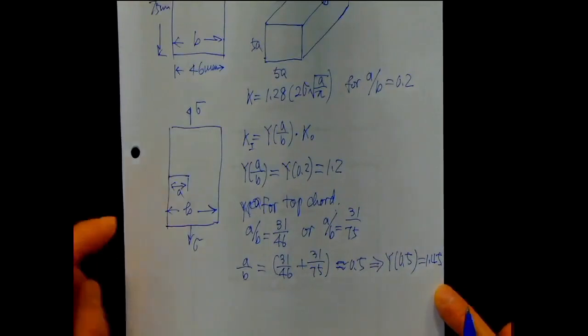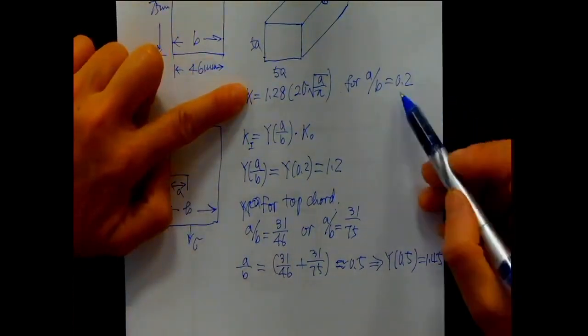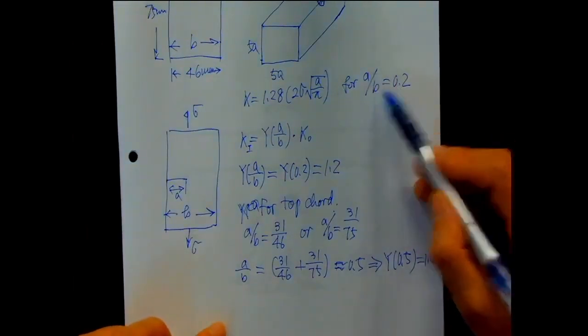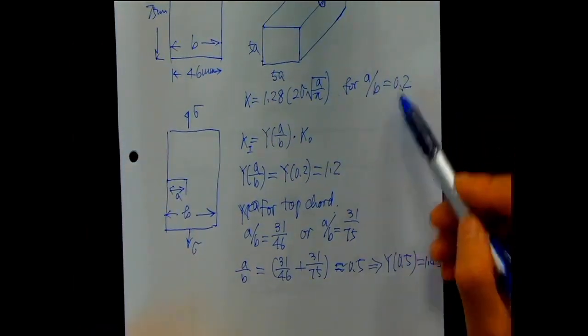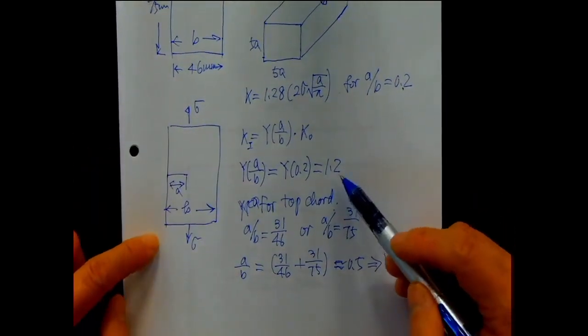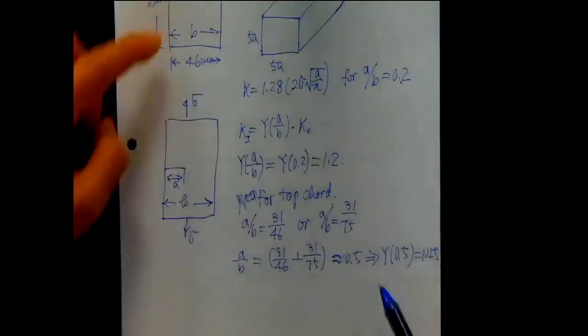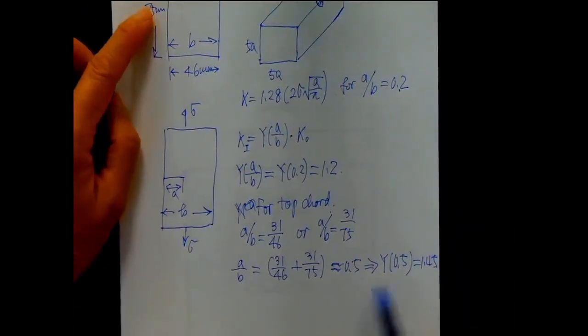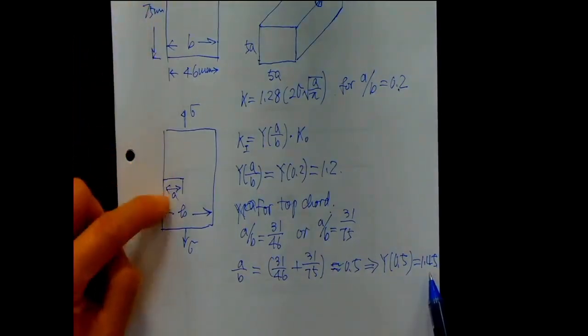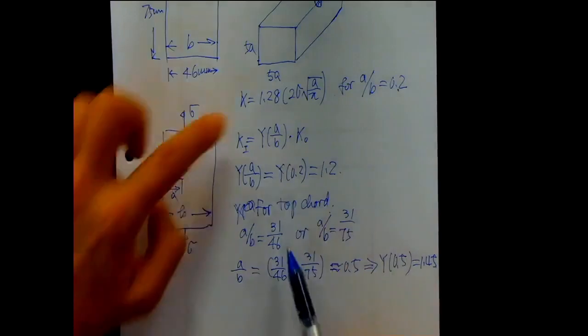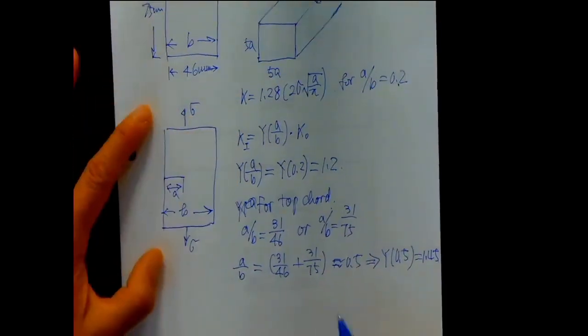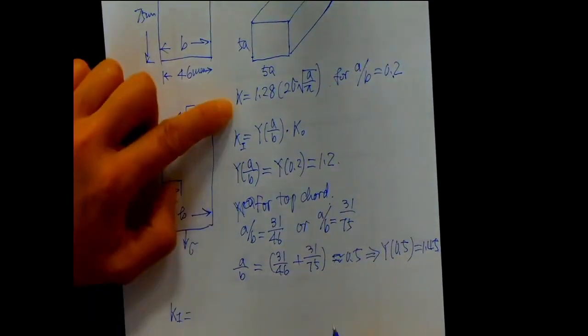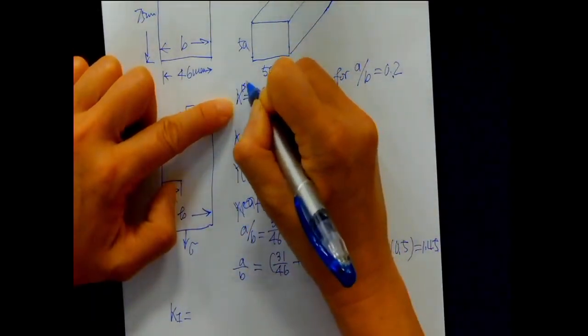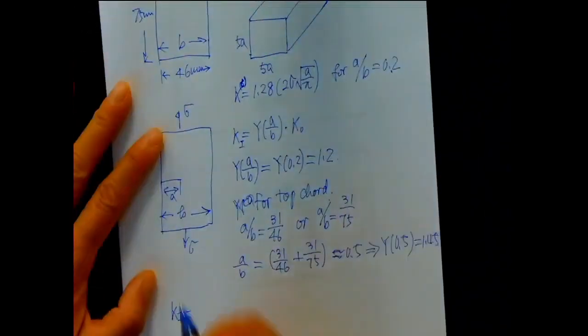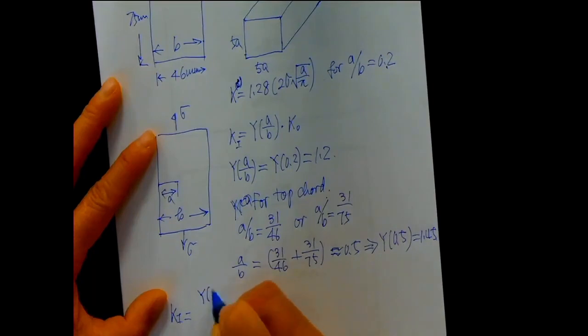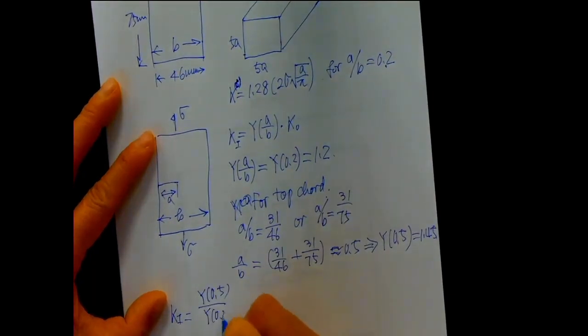And so what that tells me is my result over here is based on A over B equal to 0.2, which based on this, has a boundary effect of 1.2. But in the actual case, I have A over B equal to 0.5, so I have a boundary effect of 1.45. Okay, so what I will do is I take this and factor that in. So my K1 is going to be equal to, so I call this the square or calibrated, will be equal to y of 0.5 divided by 2 times.